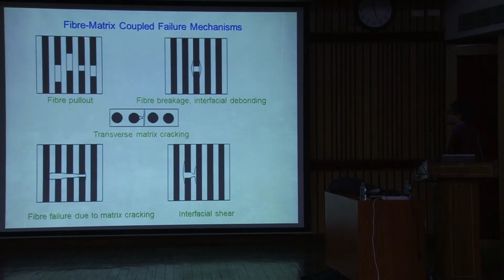Then this is the fiber matrix coupled failure mechanism. In the previous picture I showed that this fiber breaks and there is a redistribution of the stress and neighboring fibers also fail. In this case, this is a slightly different case. Let us say the fiber has failed in one region, then the stress distribution takes place and in the neighboring region, the bond between fiber and the matrix becomes weak and the fiber is pulled outside. So, earlier it was supposed to break here, but it is broken here and then it is pulled. So, this is called fiber pull out.